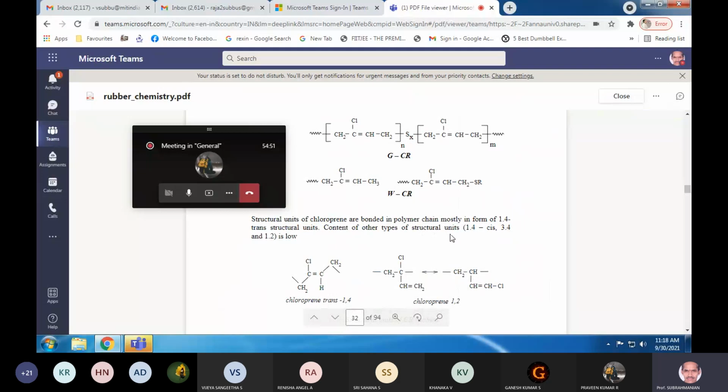Yes. And in the last class, friends, we were looking at chloroprene rubber in two different modifications, sulfur modified, mercaptan modified. So G type sulfur modified, peptizable. W type mercaptan modified because it is capped with the alkyl mercaptan. And the G type, we have a polysulfidic link.